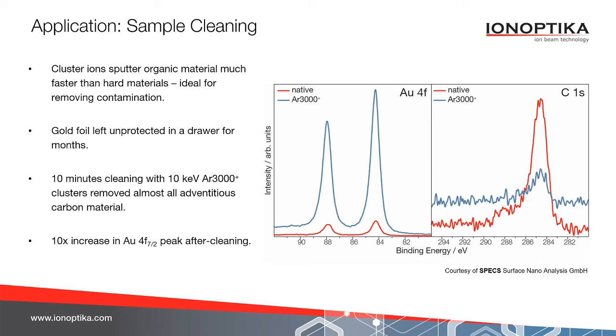We also see a 10 times increase in the signals from the gold, which shows that the carbon material was suppressing that gold peak. So it's a very simple but very powerful means of providing the best data possible. Prior to analysis, simply run a quick clean and you can guarantee that your surface is pristine.